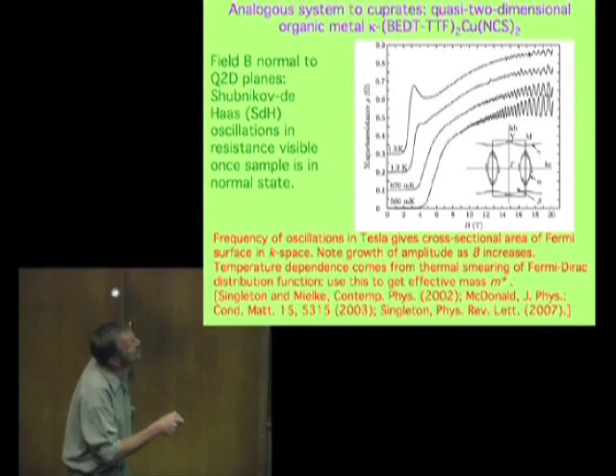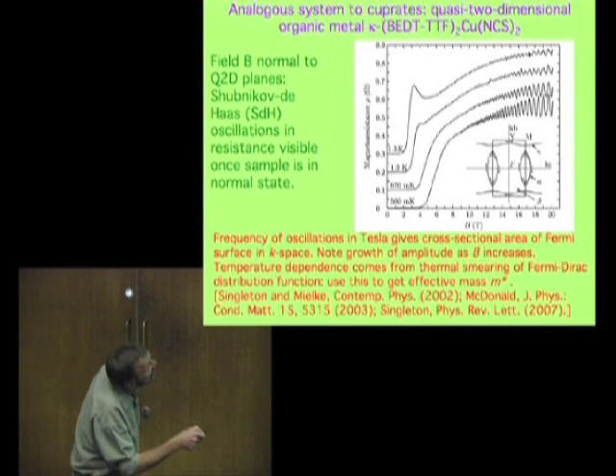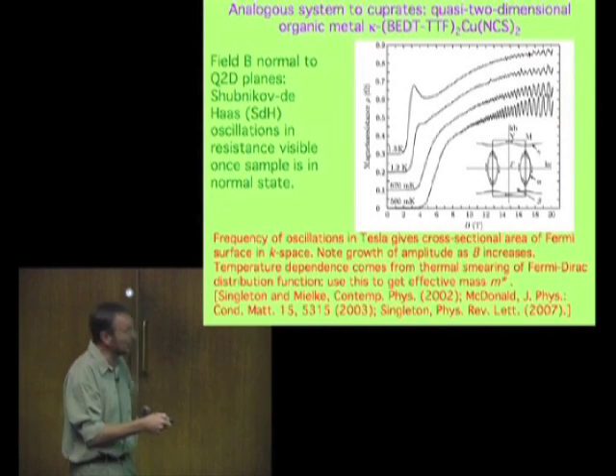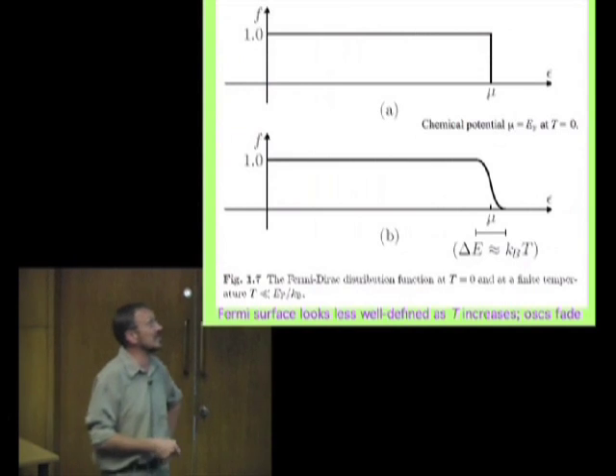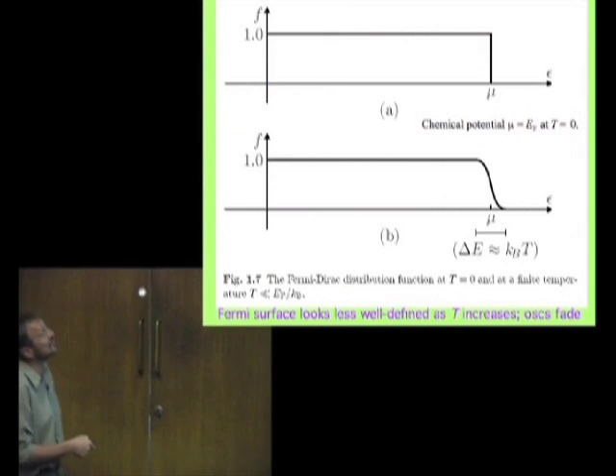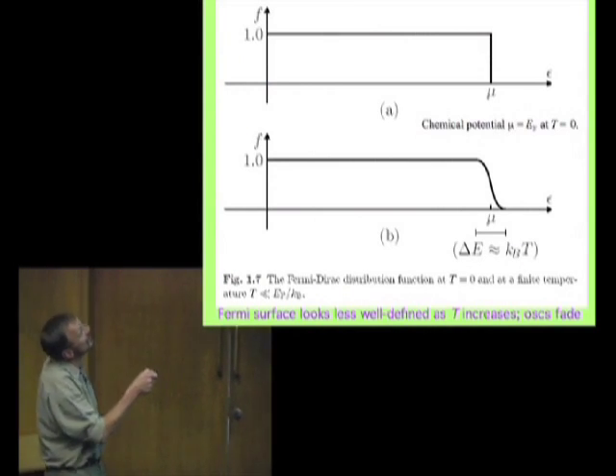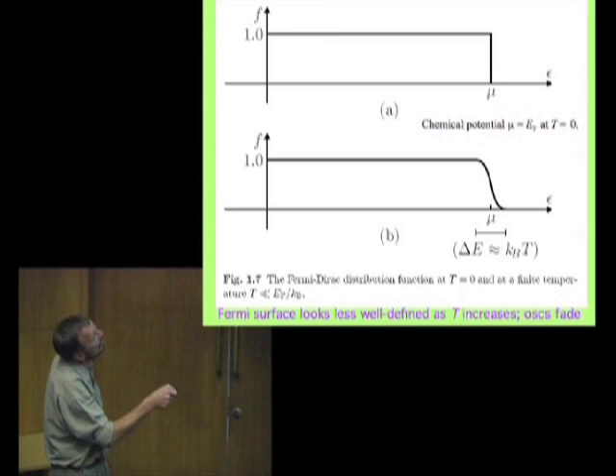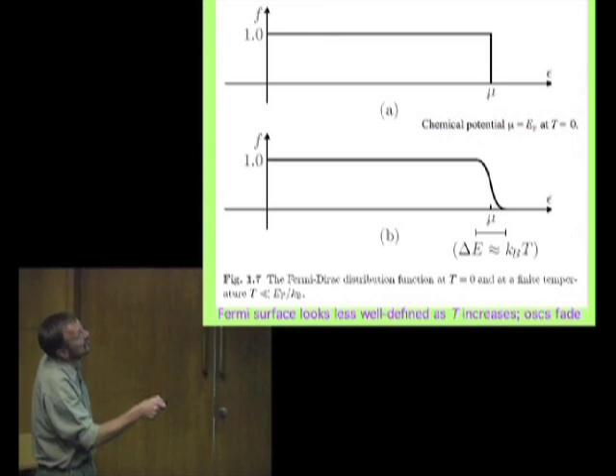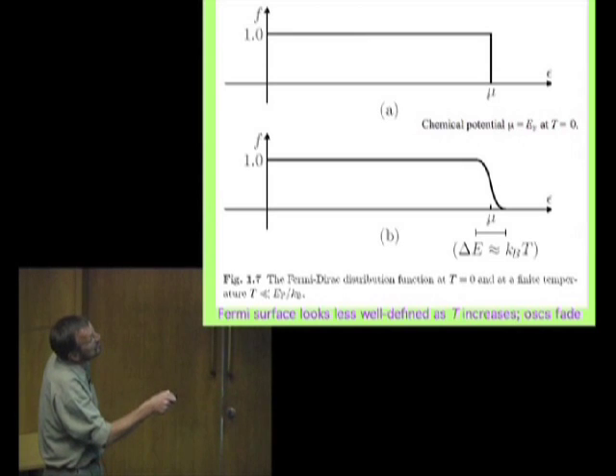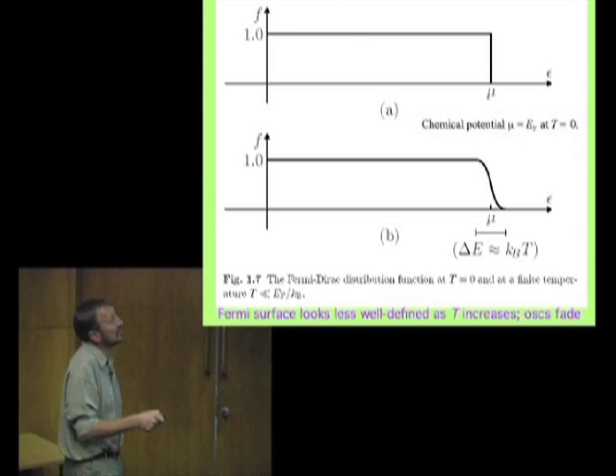The second thing you'll notice is, as we jack up the temperature, the oscillations start to go away. The reason for this isn't scattering, it's just to do with the Fermi-Dirac distribution function. At absolute zero, the Fermi-Dirac distribution function is just 1 out to the chemical potential, which is equal to the Fermi energy at absolute zero, and then it drops like a stone to 0. So the Fermi surface is very sharp.